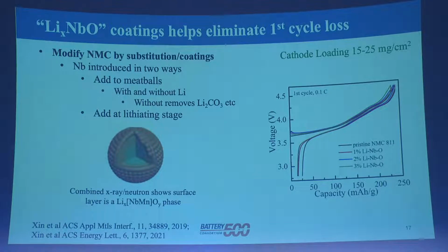And what we've been doing, we looked at aluminum to do this, and it works to some extent, but we've been particularly looking at niobium. Lithium niobium oxides are well-known ionic conductors, so we know lithium can diffuse through it, so we make a film on the surface. Lithium can still get in and out. So what we did was treat our meatballs with a lithium niobium ethoxide solution and fire it up at different temperatures. At the lowest temperature, we form a nice coating on the surface. Higher temperatures, it goes right into the lattice.